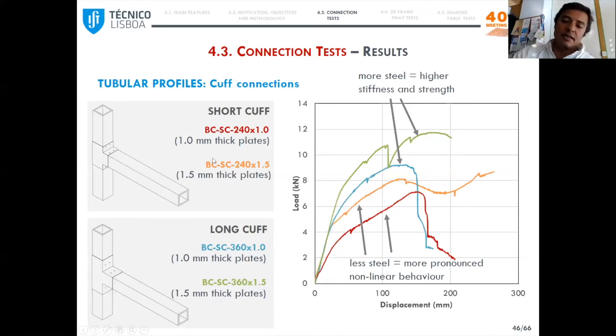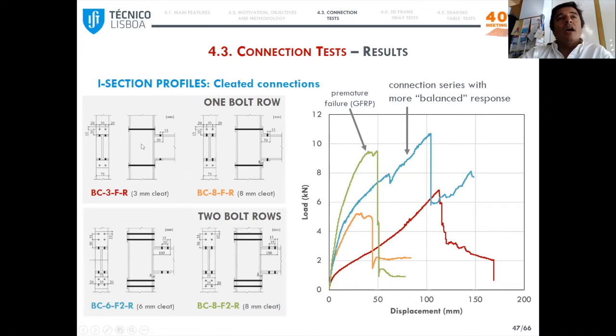Here you can see another series, the same tubular profile, but now with the cuff connection system, where we varied the thickness of the steel plate and also its length. And as expected, increasing the amount of steel increased the stiffness and the strength of the connections, but still with a quite nonlinear response. And here for the I section profile with cleated connections, where we varied the thickness of the cleats, so from 3 to 8 millimeters, and also the number of bolts.